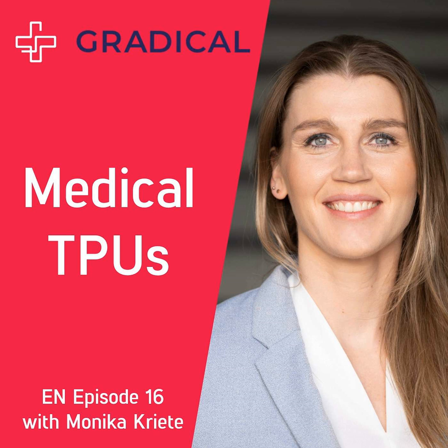We do have certain grades which are really optimized for this process, which means we take out all the other additives which you would need for melt processing, like a lubricant, for example, which could then show up as a hazy optical feature in your solution. So there are some optimized grades for that, and we see a growing demand in the last few years, that people tend to use these kinds of processes to create coatings or membranes for devices.